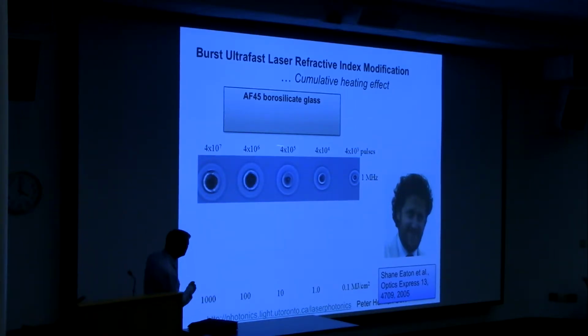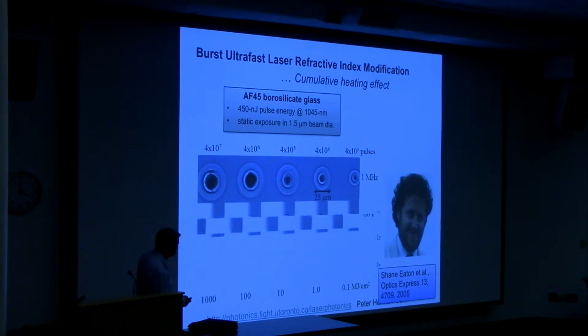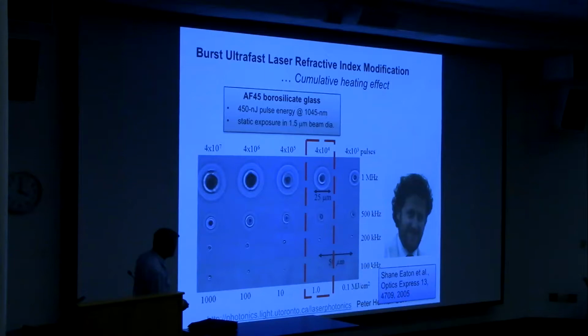What do you think happens if I repeat this exposure but at slower rates, at lower repetition rates? If I go to 1/10 the repetition rate, 100 kilohertz, notice that all the features get smaller. And in fact, the number of pulses is a weak control parameter on the morphology size. So in here, the laser focus size is about this size here, the size of the green laser pointer. And those are heat-affected zones that accumulate with more pulses to grow bigger and bigger. With repetition rate increasing just 10 times compared with many orders of magnitude on the number of pulses, we have a much bigger effect on the morphology taking place here. So when you're selecting a laser to control processes, you can't just think about the wavelength or the pulse energy or a scan speed.